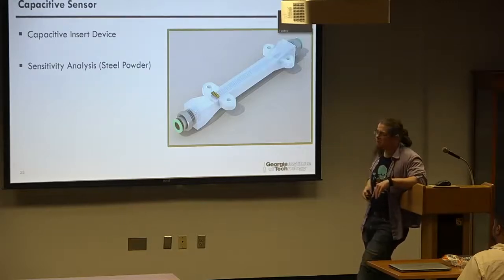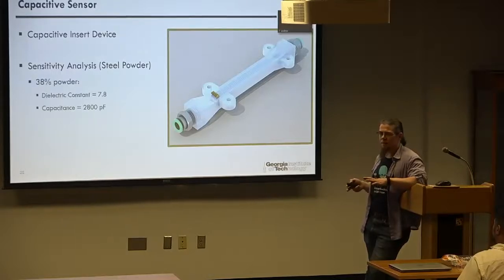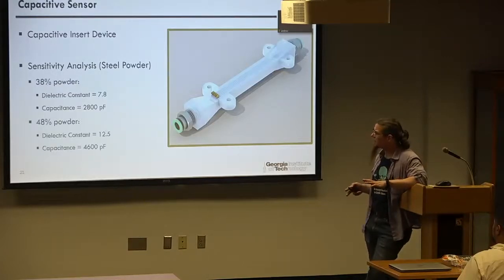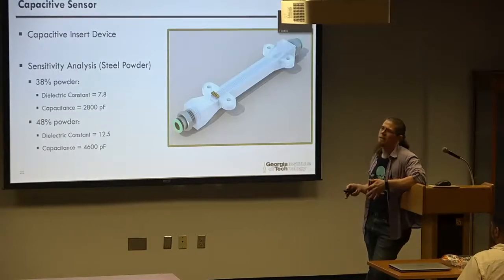If we run a quick sensitivity analysis using steel powder as an example, 38% powder in the flow volumetrically gives us a capacitance of around 2.8 nanofarads. 48% gives us around 4.6 nanofarads. So it's a pretty small capacitance that we're working with. But as far as the sensitivity of our circuits, we're expecting to be able to read this. We are hoping for 10 picofarad sensitivity with the circuits that we've set up. And so that should give us pretty strong resolution in terms of the volume fraction of the powder flow.